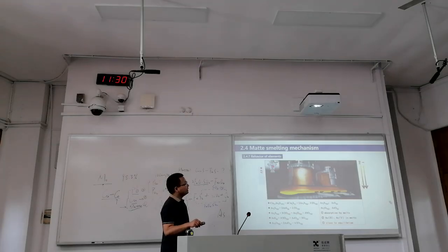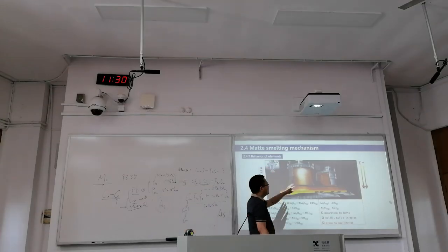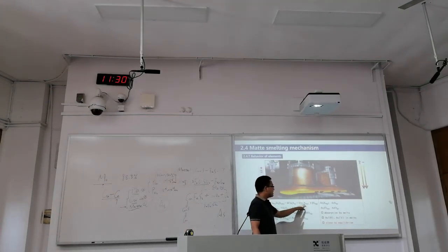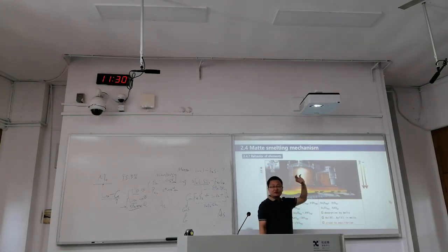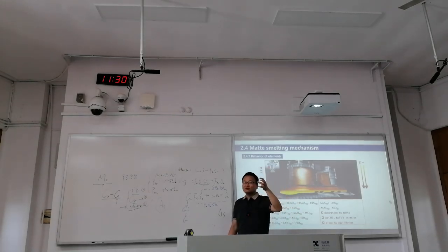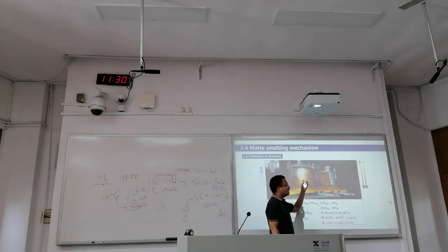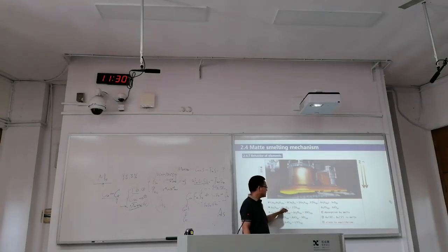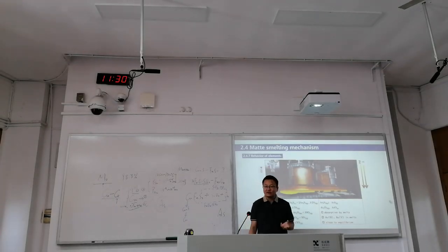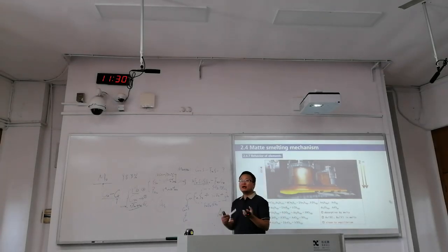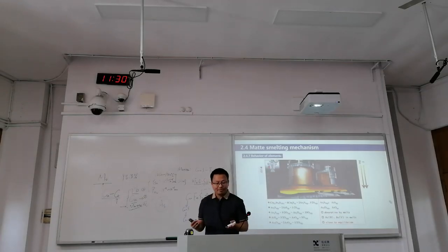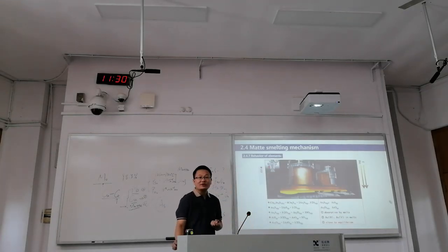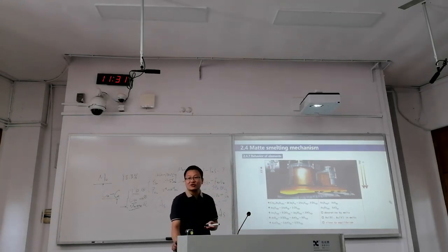So oxygen is here, decomposition is here. So we are having actually oxygen and sulfides here. This is the most dense or most concentrated region of the furnace, which is rich with sulfides and oxygen. If we have sulfides and oxygen, what will be the consequence, or what will be the following reactions?